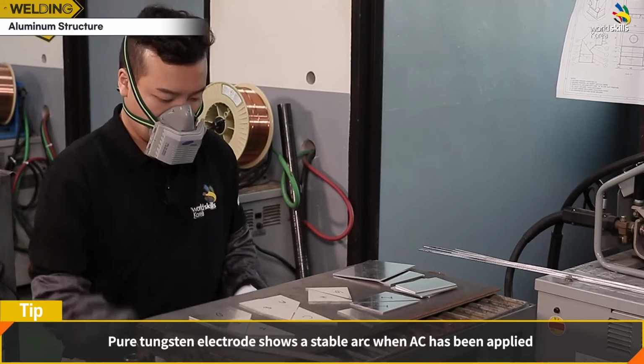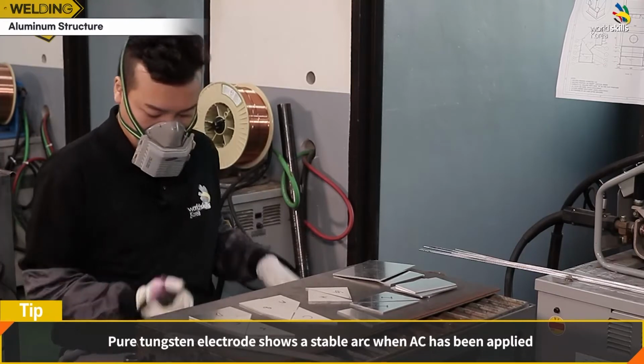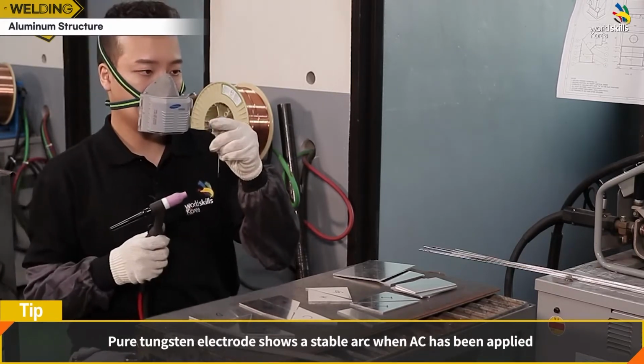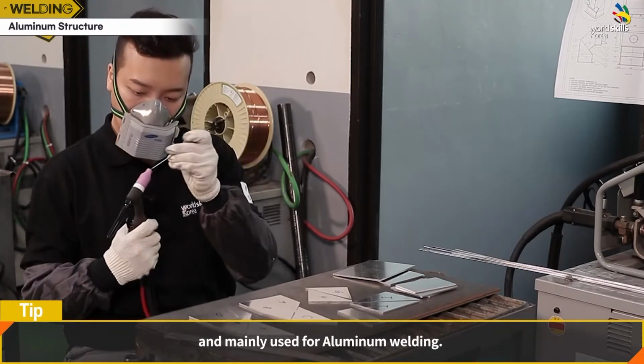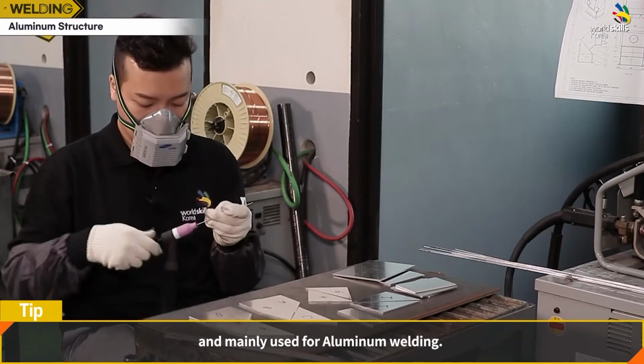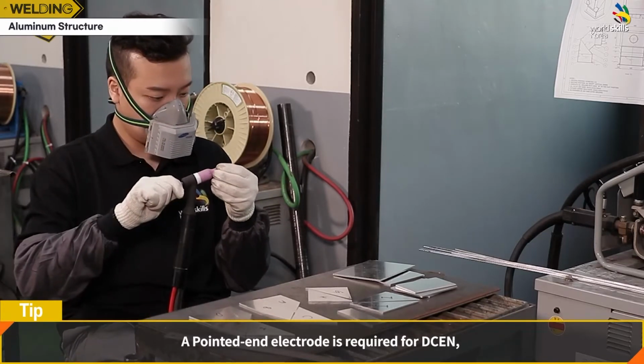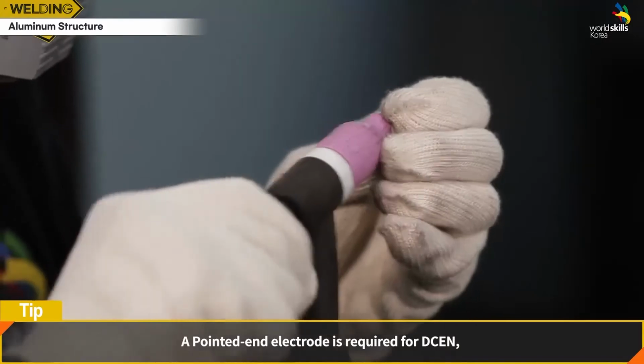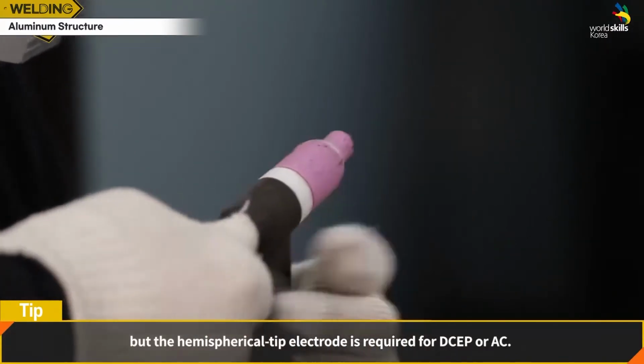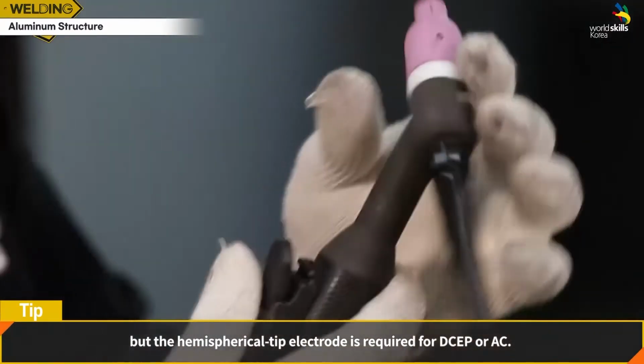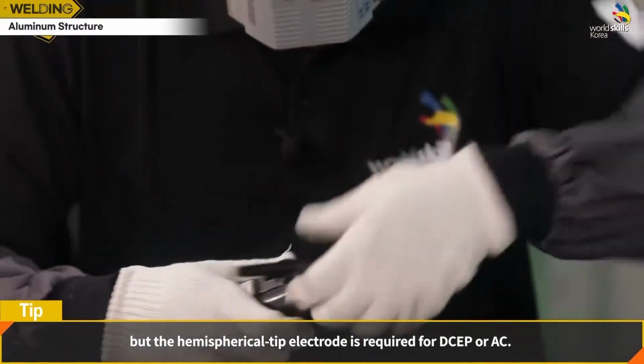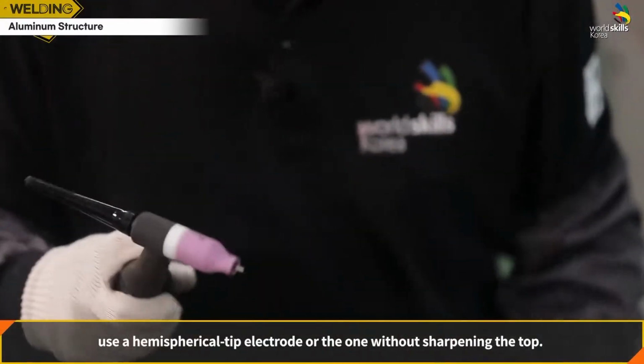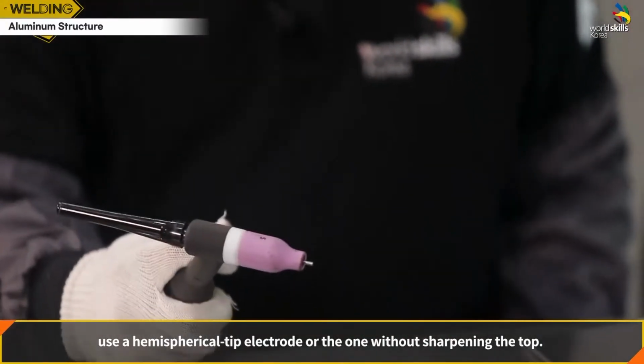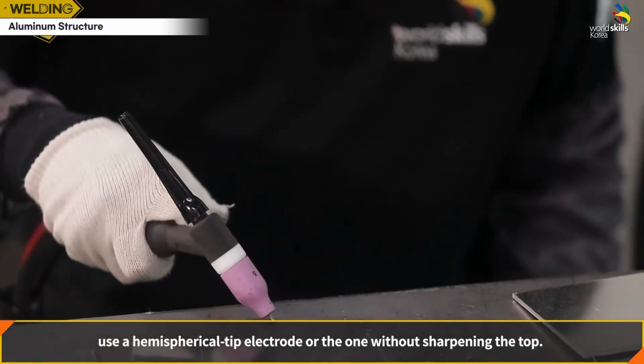Pure tungsten electrode shows a stable arc when AC has been applied and is mainly used for aluminum welding. A pointed end electrode is required for DCEN, but a hemispherical tip electrode is required for DCEP or AC. For AC aluminum welding, use a hemispherical tip electrode, or one without sharpening the top.